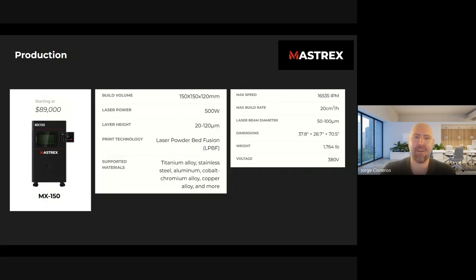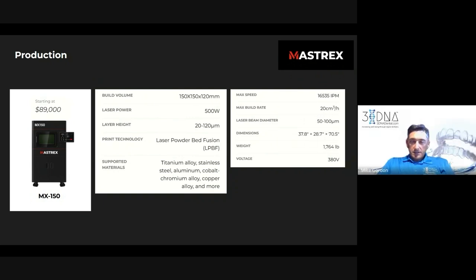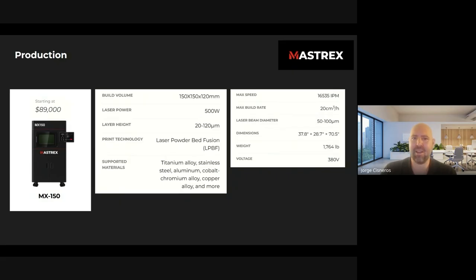And then as far as laser power goes, that starts with a 500 watt laser. So a little bit bigger laser beam and a little bit more laser power, but that allows for faster production, a little bit faster lasering of the parts. That's a single laser, or is that 2 lasers? Yes, that is also a single laser. Yep. And then you can see the laser beam diameter is slightly larger, starts at 50 microns. Overall, that won't have much effect on your tolerances or the part.